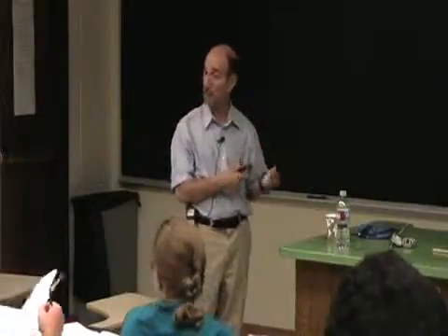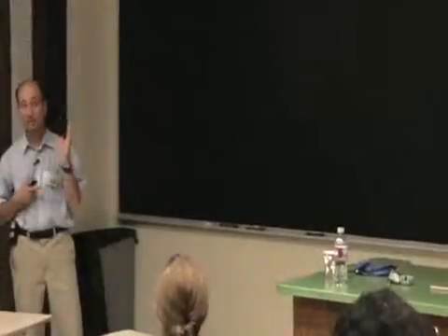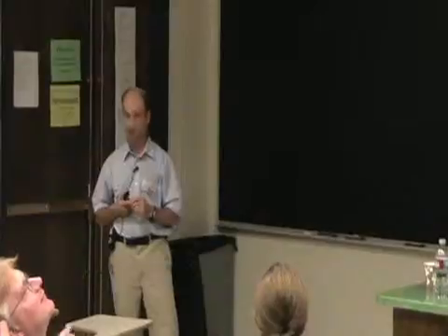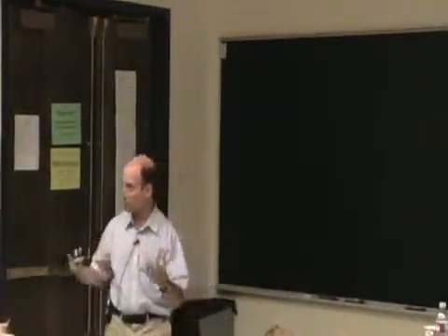I was going to show you ferromagnetic resonance. You can see that in the notes. You see a very nice absorption if you apply RF, either sweeping the frequency at a fixed field, or applying a constant frequency and sweeping the magnetic field. You can use that to measure the energetics, the form of the anisotropy of the magnet. You typically do that in a large field, so it's a good approximation to assume that the magnetization is uniform across the sample.